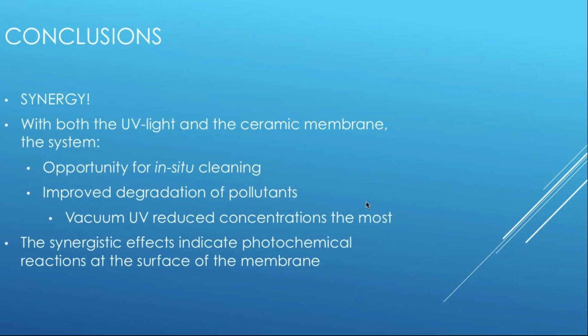And this is probably likely because of the photochemical reactions occurring on the surface of the membrane, caused by the UV light. We did XRD analysis, and it suggested the surface of the membrane was rutile. It's pretty common for certain ceramic membranes to utilize titanium dioxide in not only their support layers, but their active layer as well.